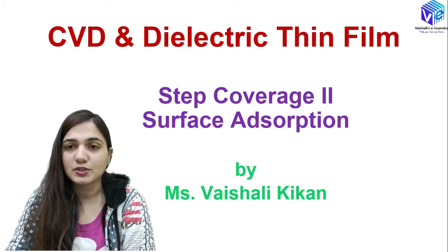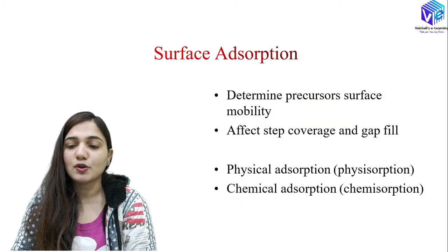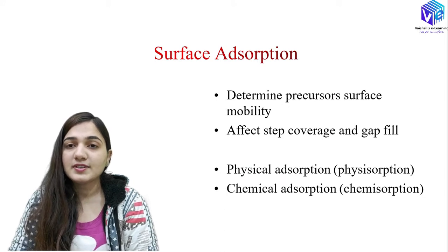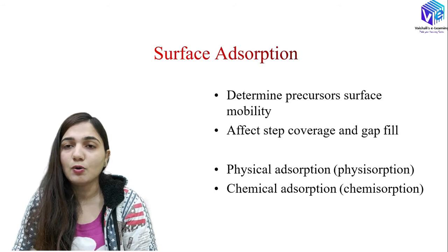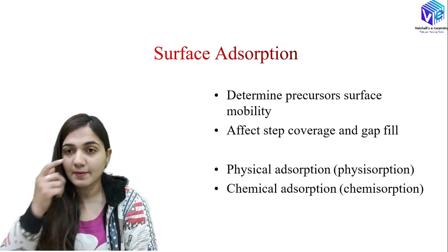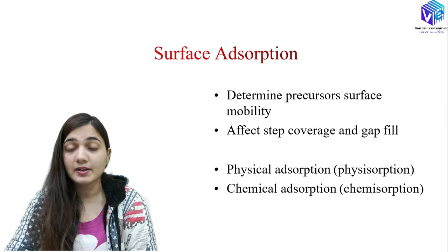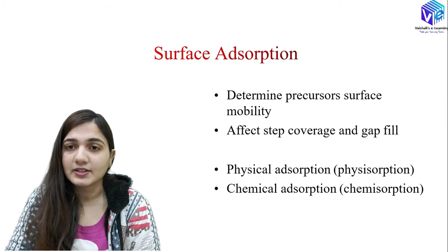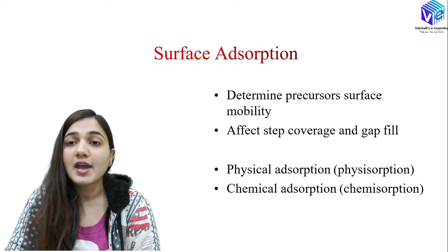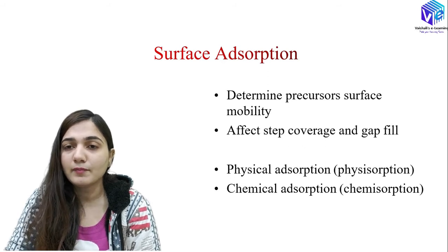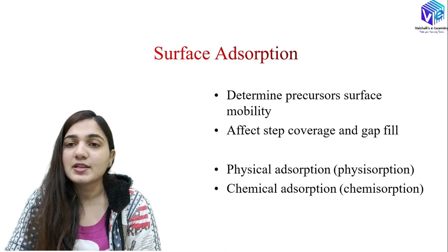of surface adsorption. We must know what surface adsorption is. Surface adsorption is a very important thing which determines how the step coverage will form, and how uniform the step coverage will be with the dielectric thin film. It is determined by the surface mobility. How much is the surface mobility of the precursors? It determines how uniform a thin layer we are depositing. So it affects the step coverage as well as gap fill.